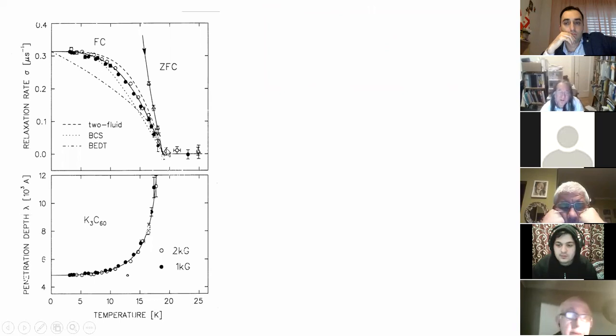Okay. So anyway, if you do this measurement, I hope you remember that we saw some damping, and this damping happens only below the superconducting state. So if you measure this damping rate as a function of temperature in this potassium 3C60, the damping rate increases when you enter the superconducting state or below the superconducting transition temperature, and show this kind of temperature dependence. And so because this damping rate is related to inverse of the penetration depth square, just measuring the damping rate immediately allows us to determine this important length scale, the penetration depth.